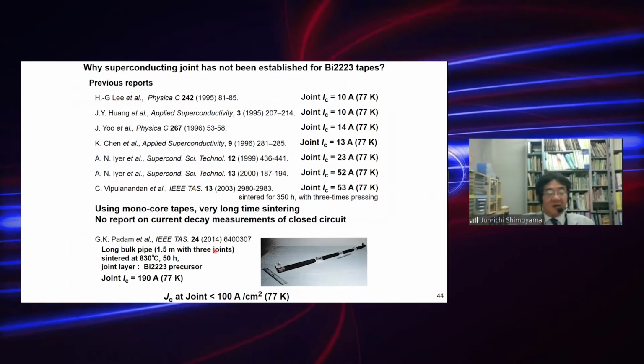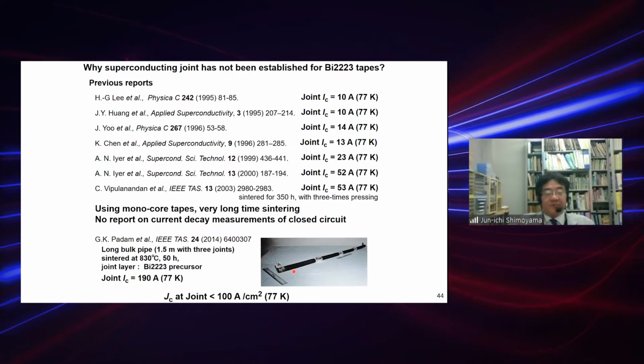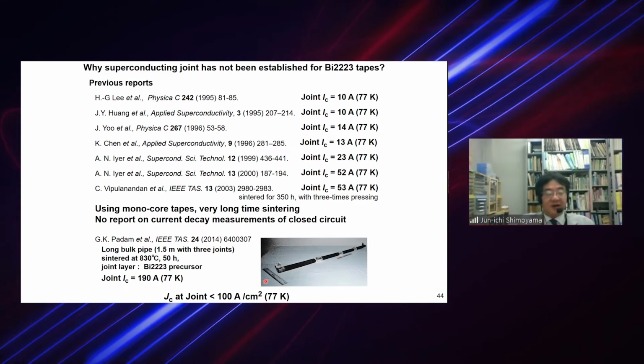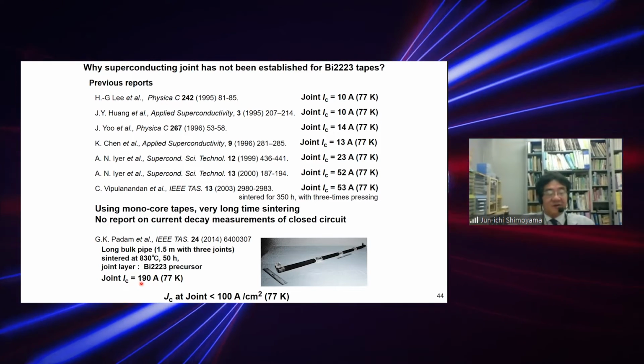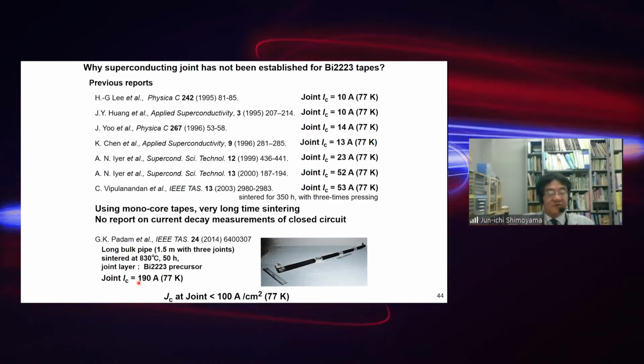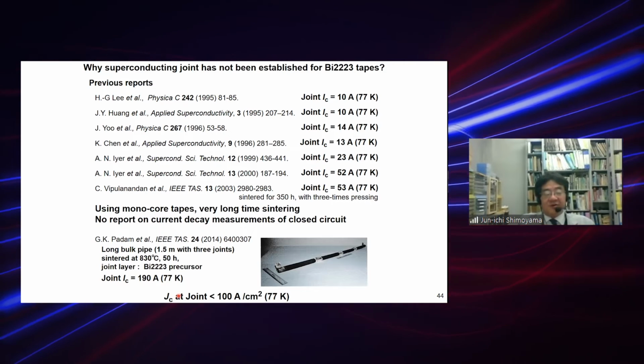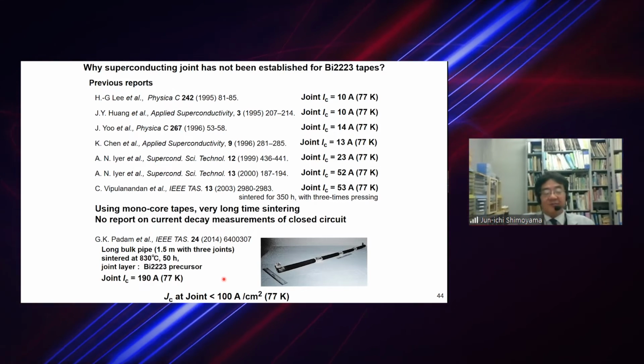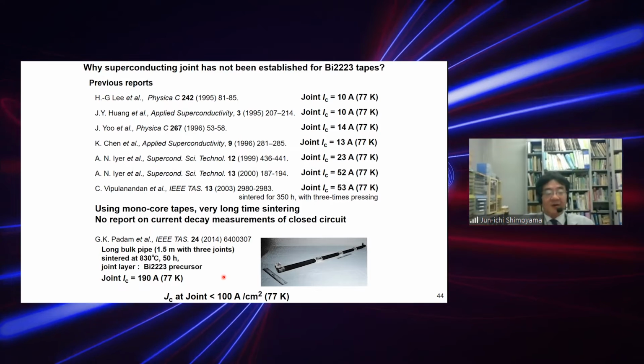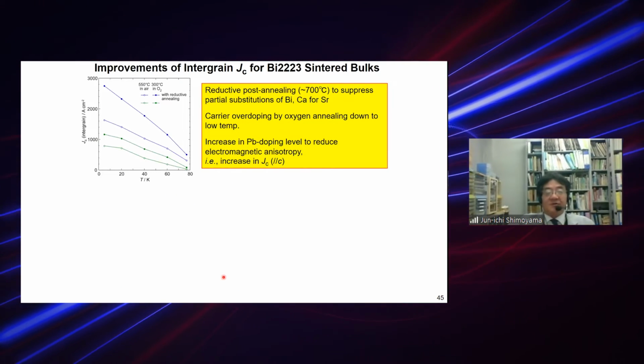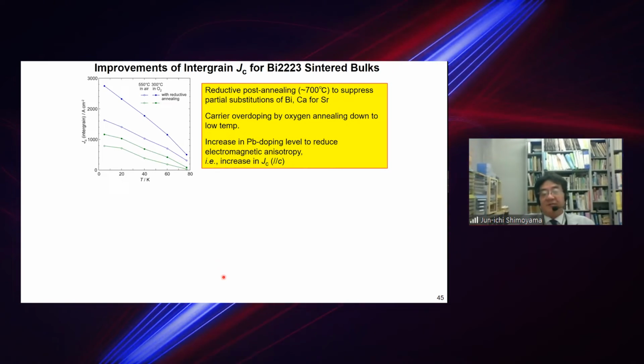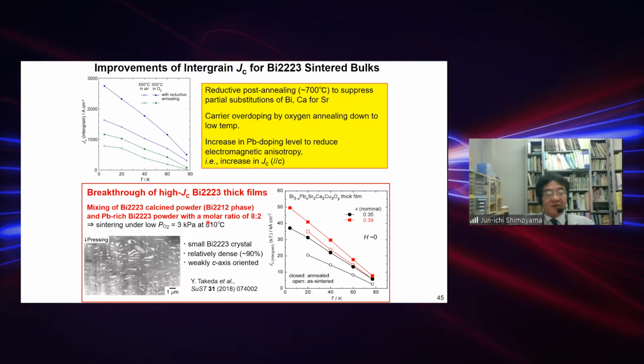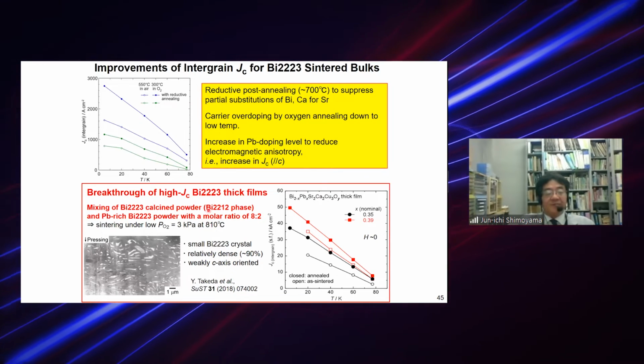But we found very large joint Ic for the bulk materials, as you see here. In this case, joint Ic is close to 200 amps, but the joint Jc is not so high, 100 amps per square centimeter or something like that. Anyway, we must develop a good joint method connecting Bi-2223 multifilamentary tapes.